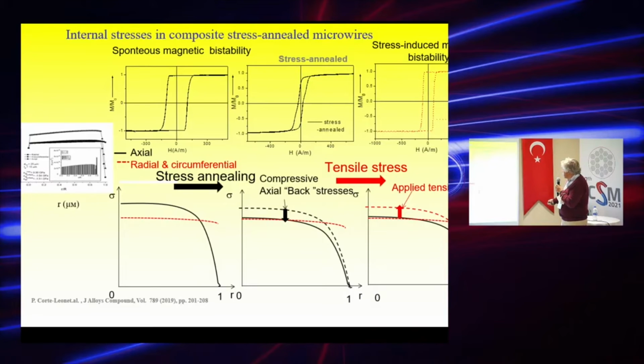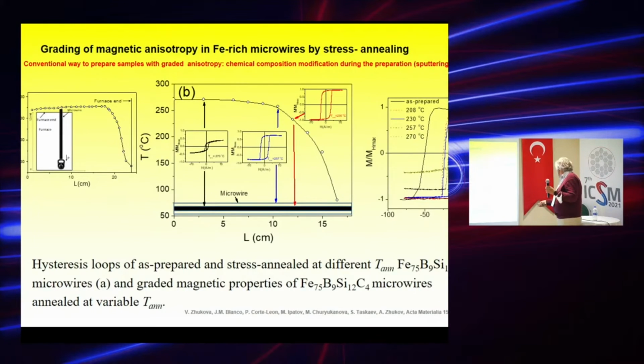And now, if we apply stresses during the measurements, we recover this hysteresis loop because the axial stresses become again the highest one, and this can explain the change of shape of the hysteresis loop and also the stress sensitivity of our materials. Another important issue, it might be a couple of slides more. So we were able, using stress annealing, to make so-called graded magnetic anisotropy.